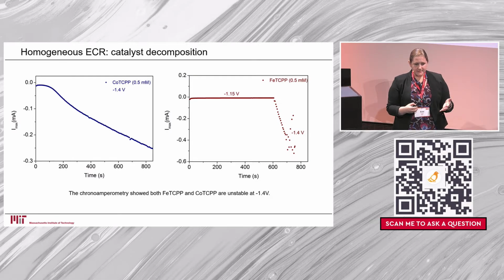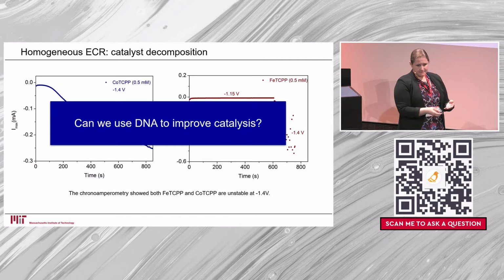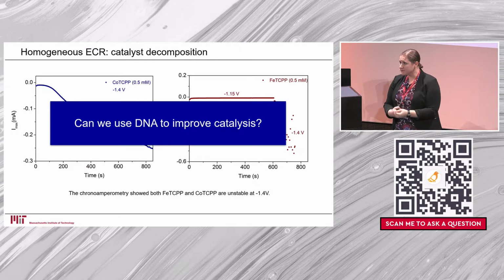The problem is these catalysts degrade nearly immediately. So within seconds, we see this current change, which indicates those catalysts plating onto the electrode and ruining both the catalyst and the electrode. So although these catalysts have been used for years to show small-scale transformations, they really haven't been industrially viable. So we wanted to think about whether we could actually use the inherent materials properties of DNA to improve this catalysis.